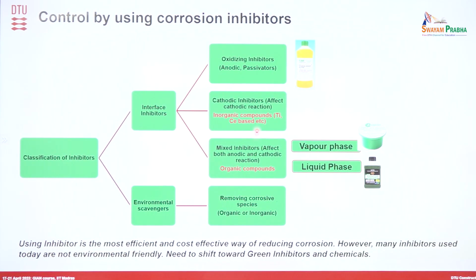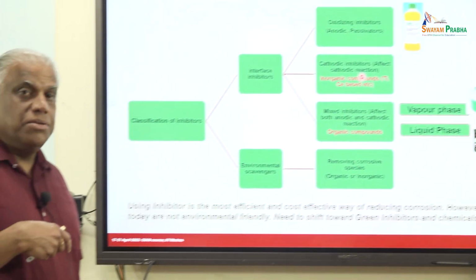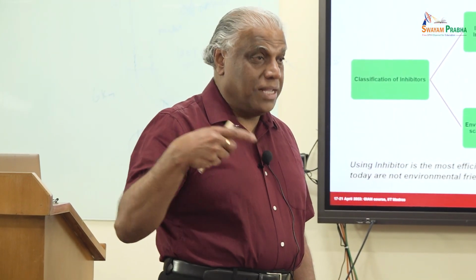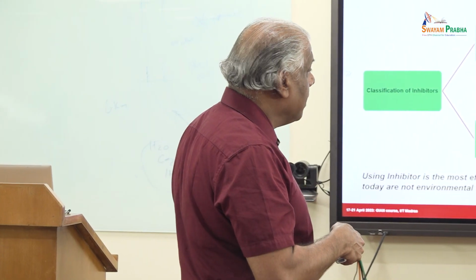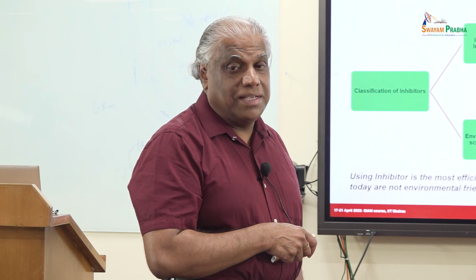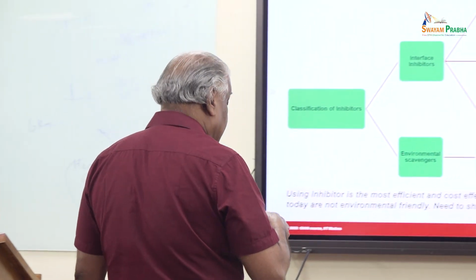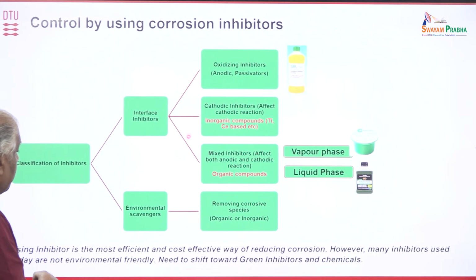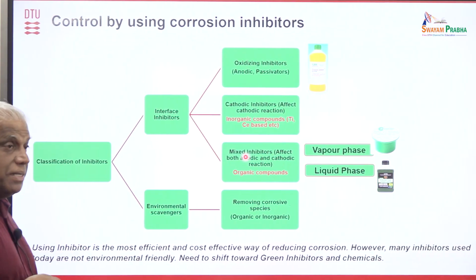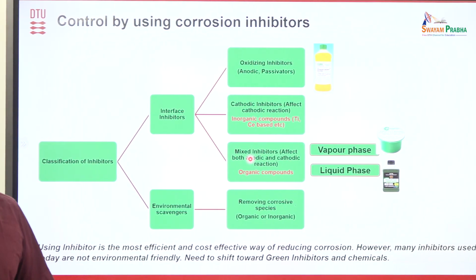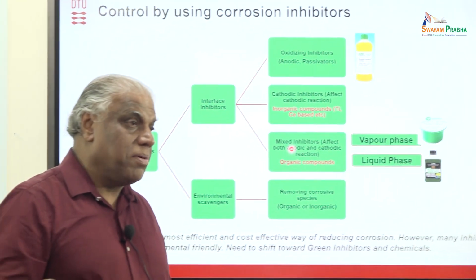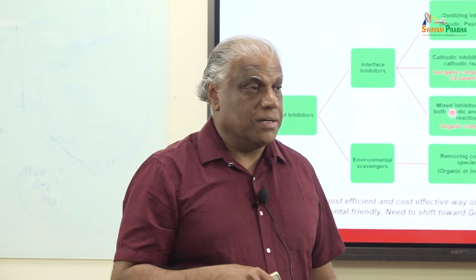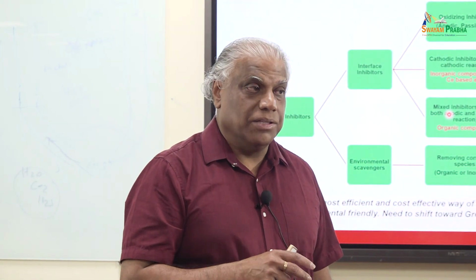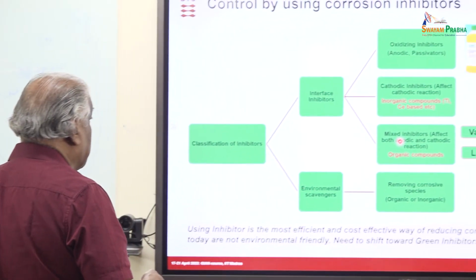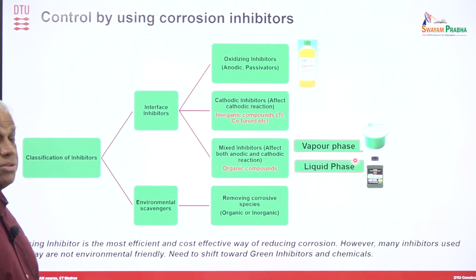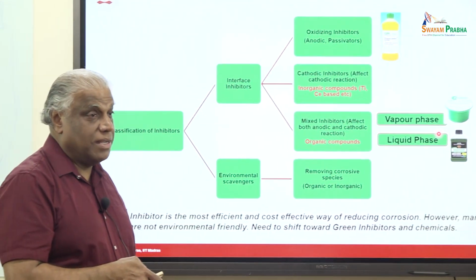And this technology has been available for a long time, and today when people are trying to replace the chromium in the coatings, people are also trying to make this into a conversion coating as well, instead of just using it as an inhibitor. I'll come to that. So that's blocking the cathodic site. But mostly the major use of inhibitors is for mixed inhibitors, where both the anodic and cathodic sites are blocked. Basically it forms an adsorbed film on the surface of the metal, and that way both the anodic and cathodic reactions are reduced. There are so many chemicals they use today for these mixed inhibitors, but all these also have environmental effects because they are poisonous and things like that.